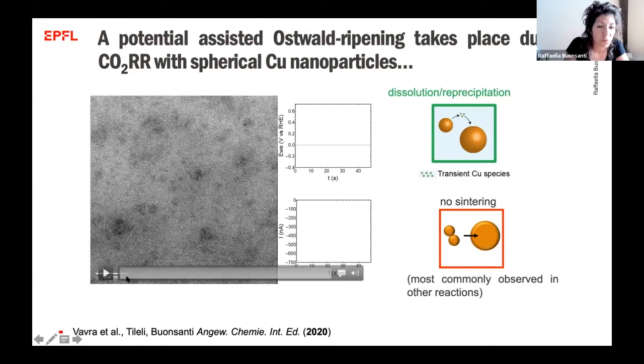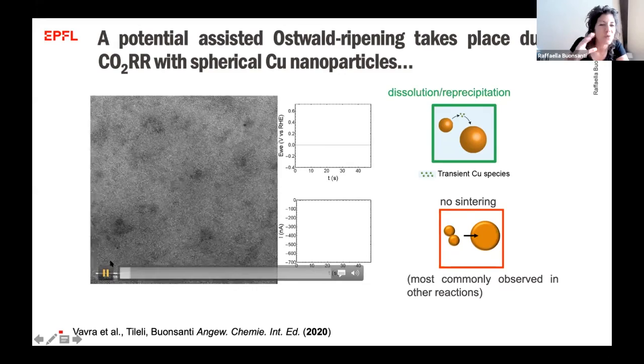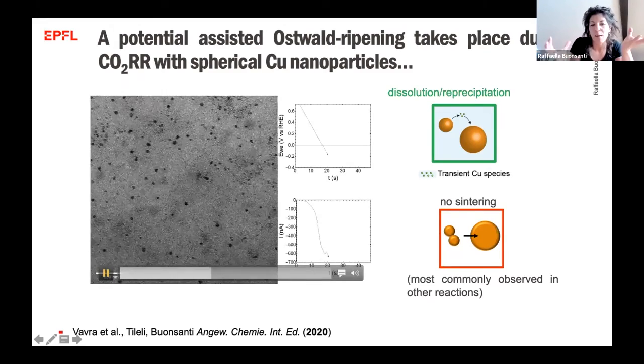And so in collaboration with my colleague in the material science department, Vaso Tileli, we performed some in situ electron microscopy in liquid. Of course, this has nothing to do with the beautiful images that Sara showed, but it's also more complicated because we are applying a bias. There is a liquid layer. And so the only thing you can see here is that during electrochemistry, these particles become bigger.